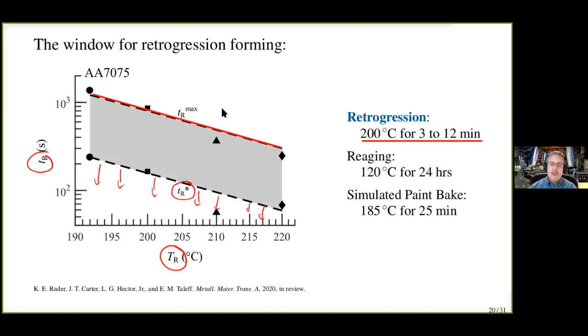Now, after forming, just to remind you, we would try to re-age at this temperature right here. So we try to re-age at 120 for 24 hours to get the full strength back. And that simulated paint bake I talked about before, which we keep trying, is 185 for 25 minutes. That's about what one type of paint bake process uses. We do find it doesn't work particularly well for 7075, but it's better than doing no re-aging at all. So again, this is just a practical interest for us.